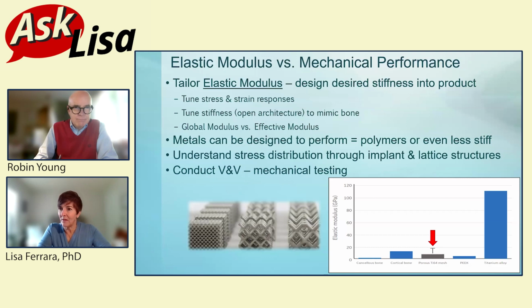Now we're getting to that next level of real finesse with those patient-specific implants. We can design these structures. So when you look at the three below, it's all the same titanium. They're all printed, but you can see there are three different open architecture areas. And they perform very differently from each other. Why? Because we're looking at a structure that, yeah, it's titanium, but it's open. We can have strain or displacements in these little struts so that you'll get more motion microscopically, obviously. And it will, when tested, actually show to be less stiff, perhaps, than even PEEK.